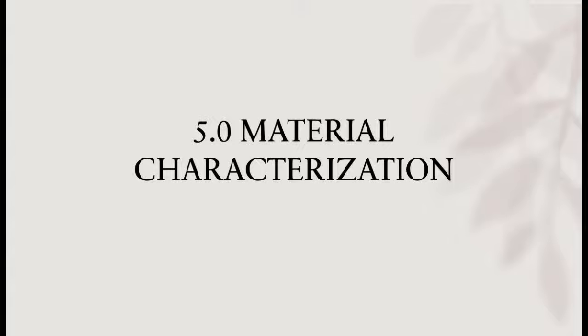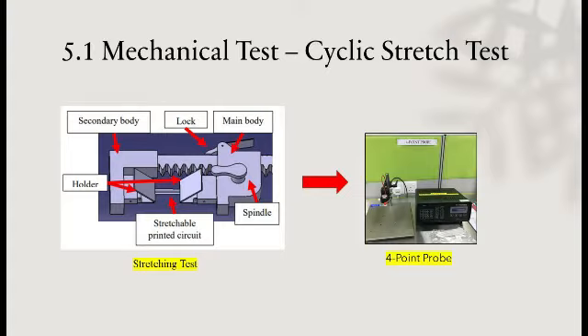Next, I will be presenting the material characterization. The material characterization will be determined by running tests for the subjects. First is the mechanical test, the cyclic stretch test. The stretch test is performed on substrates such as TPU and PET to evaluate the electrical performance of the stretchable conductive ink for every 1000 cycles to 5000 cycles until it is fatigued. It is important to determine the flexibility of the substrate with the filler after a few cycles of the test.